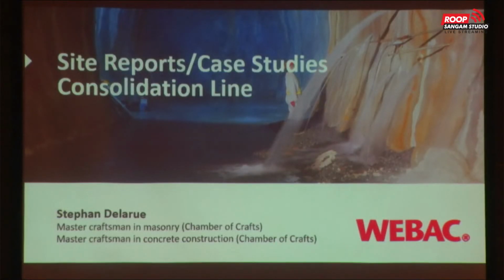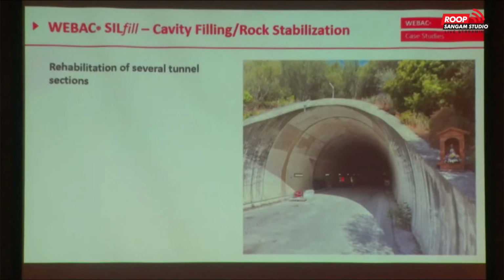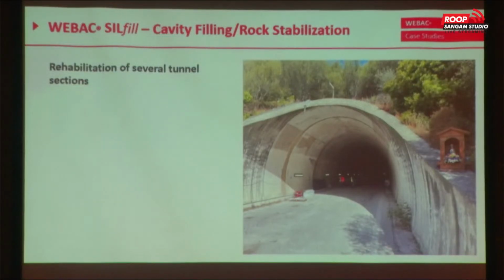So you remember that picture, we come to that later. So first, you start with a silicate foam resin. Sorry, I forgot, silicates are cuttable, and this is an important point if you have to strengthen or inject in front of a TBM, for example, because this gives the option of the TBM cutter head to cut through that consolidated area. If you would use a big amount of polyurethane resin, maybe there is the risk that the cutter head gets stuck because of the gluing effect. If a polyurethane gets warm or heated, it will start gluing, and maybe that gives you some difficulty for your cutter head of the TBM, microtunneling, whatever it is. Therefore, silicate resins are designed to drive through, to cut through, and to dig through that consolidated area.